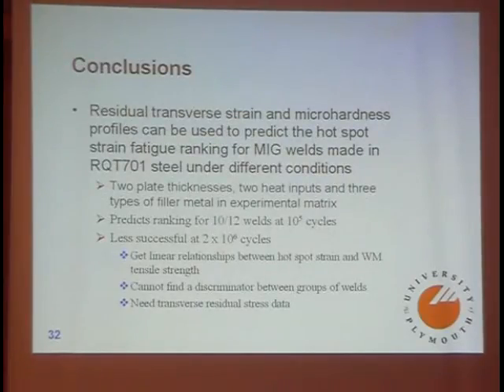So, pretty much on time. My conclusions are that residual transverse strain and micro-hardness profiles, and you could say stress instead of strain there, can be used to predict the hotspot strain fatigue ranking for MIG welds made in this roller quench and tempered steel under different conditions. As I say, we've used 2 thicknesses, 2 heat inputs, 3 filler metals, and we get the fatigue ranking for 10 out of 12 welds at 10 to the 5 cycles. And while we're less successful at 2 million, we do get linear relationships, e.g. between hotspot strain and tensile strength. But I need a discriminator to work out between those.